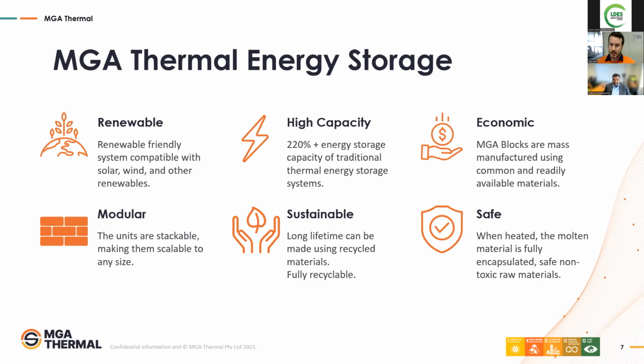The modularity allows us to stack them up into very large storage systems or to go down quite small very easily. Sustainability I've covered, and safety. It is an important issue to cover, especially with the use of phase change materials. Typically, if you have a very large volume encapsulated, then you risk rupture if there's any sort of failure of your encapsulation mechanism.